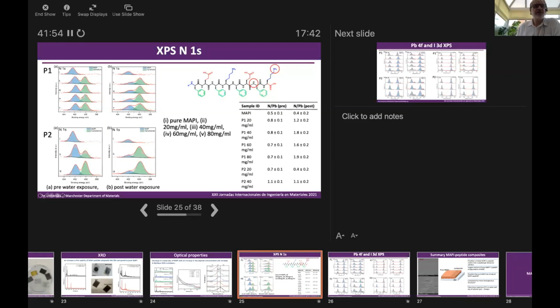When we expose to water, so this is pure MAPI, this is the lowest peptide loading, and this is the highest peptide loading, you can see that as we increase the peptide loading, the relative intensity of these two peaks stays similar to what it was before. There's an additional complication here because we don't know for sure what effects the water vapor has on this peptide. Whether the water vapor actually leads to protonation of some of these amine groups, and that then leads to, firstly, a broadening of these peaks, and also it may be that we get a shift in spectral weight from one of these peaks to the other. When you form NH3 by protonation, you get a higher binding energy peak, so some of this intensity transfers to this particular peak. So that's something we need to do next.